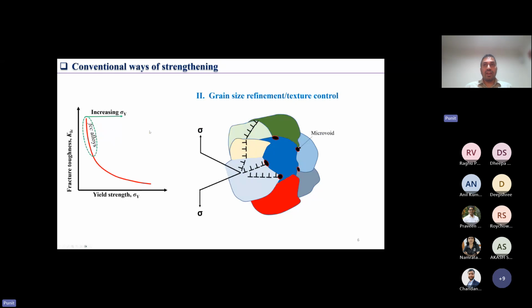we can try grain refinement through material processing. And in this case, there are two possibilities. For example, your grain boundary is blocking the movement of dislocations, and that would increase the strength by the Hall-Petch mechanism. And at the same time, you can nucleate a different slip system in the neighboring grain, and by doing that you can still spread the deformation or plasticity or damage away from the crack tip through this route. And this usually happens if you have low angle grain boundaries.